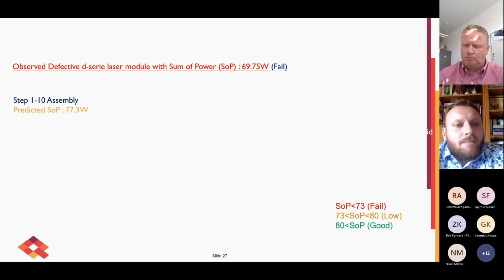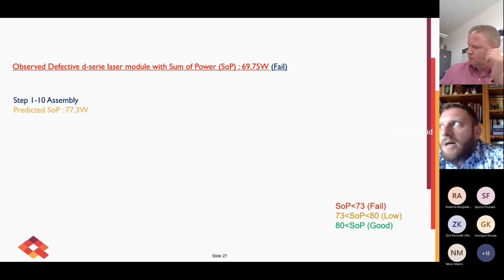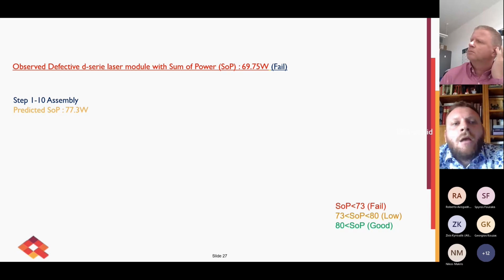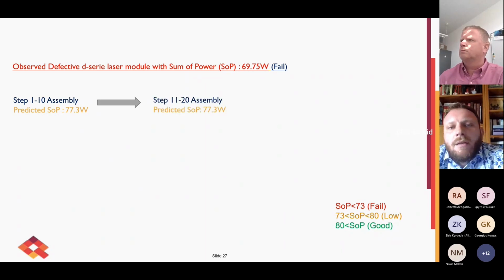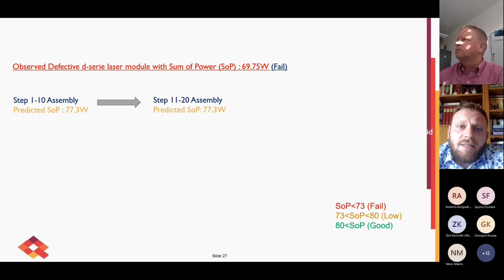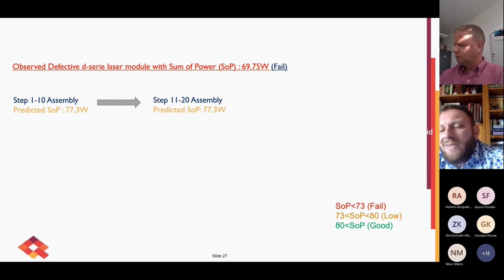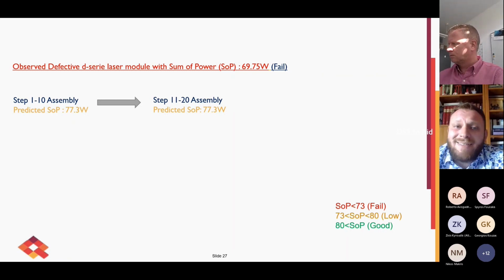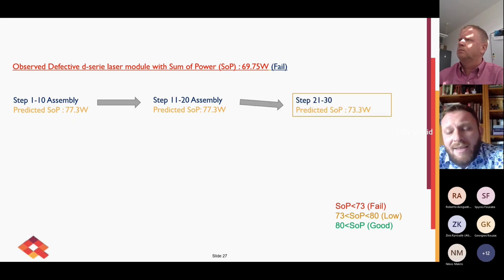So in the first steps of the assembly, steps 1 to 10, we predict 77.3, which is low. So far, no defect has occurred in the assembly, and we can proceed carefully with the assembly of that module. In the second stage, in the second crucial step, which is step 20, we again predict 77.3, meaning that everything is going as planned so far. We're going to have a low power module in the end, but still there is not a defect that puts it under the threshold. Here, at the third crucial step, we can see that the predicted output power is falling.